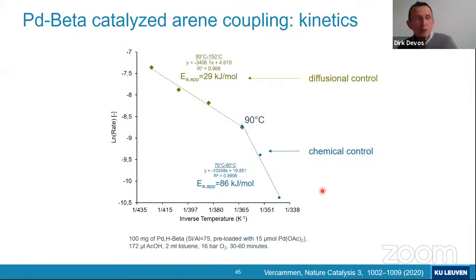We looked a lot at the kinetics also to understand the system better. And of course, you hope from the kinetics to deduce some information regarding the mechanism. First of all, because you are in a porous material, you need to ascertain that indeed you are in chemical and not in diffusional control. Then you can make these plots of the ln of the rate versus the reciprocal temperature. And it seems that as long as the temperature is low enough, you are in chemical control with a pretty high apparent activation energy.